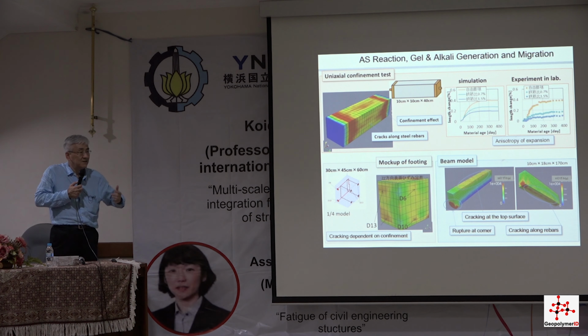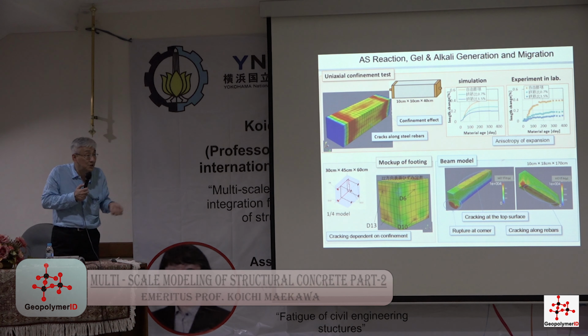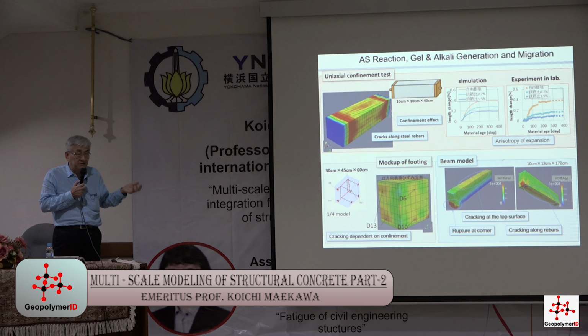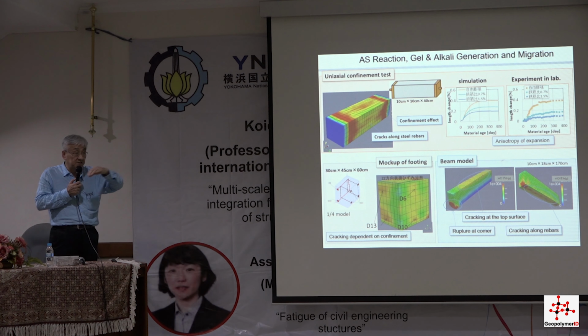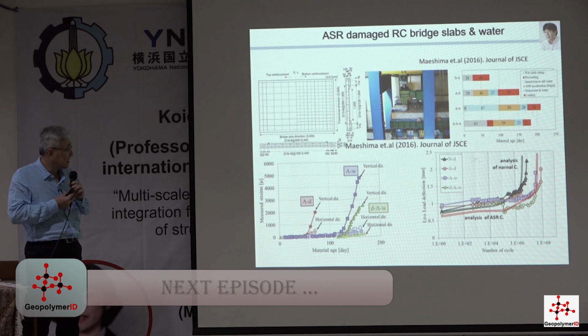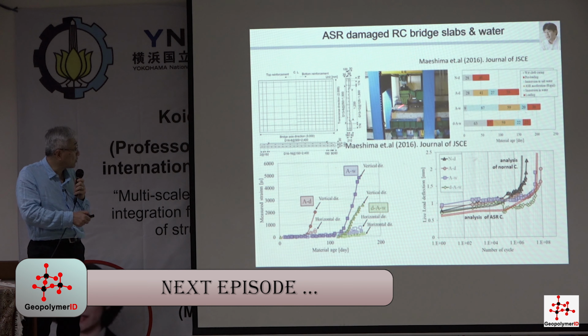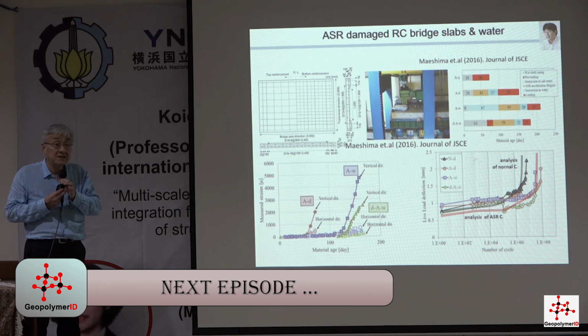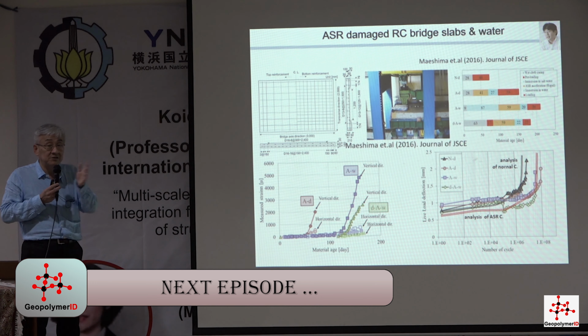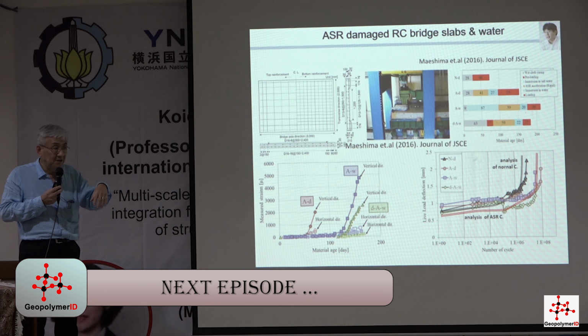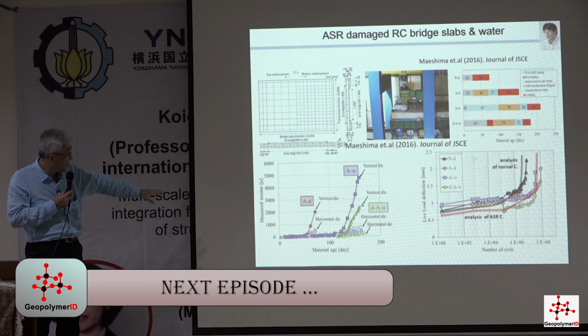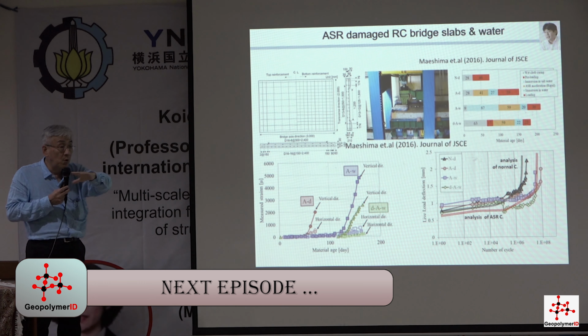Yeah. At the same time, this has been known from experiments in railway engineering. The same thing was predicted for bridges. But ASR is very miserable, with so many cracks, but the life of the structures is prolonged. In the case of normal concrete, if we have water on the structures, I said that life is shortened about 100 times, 1,000 times shorter. But when we put water on an ASR-damaged structure, and a priori,